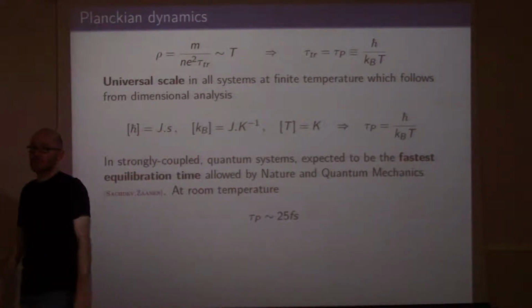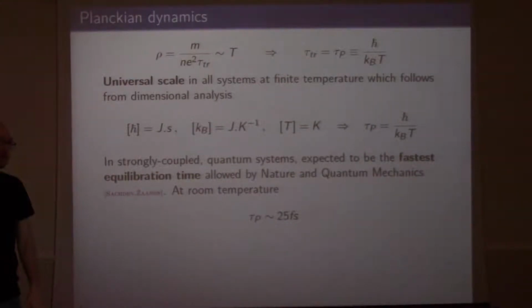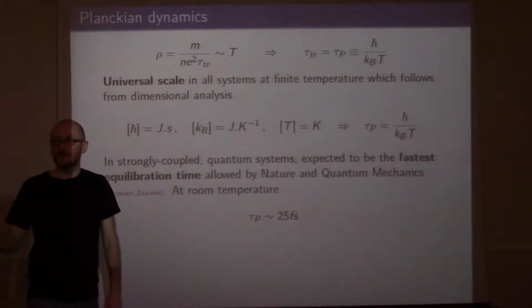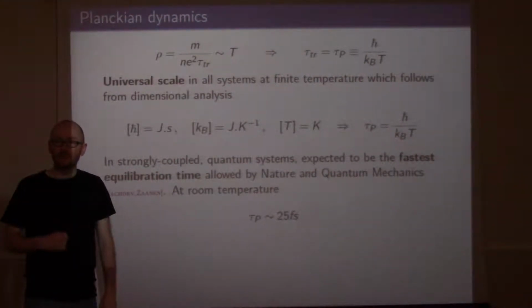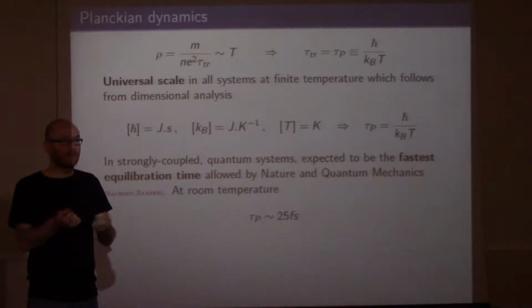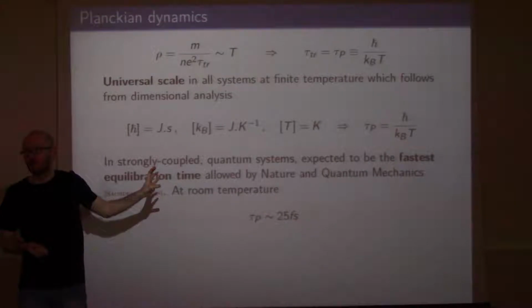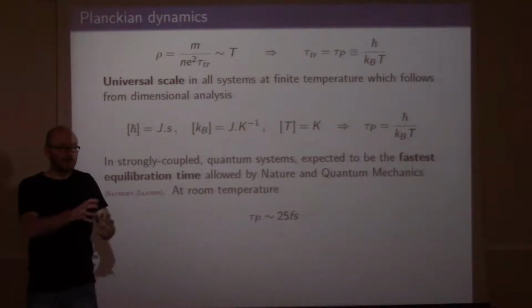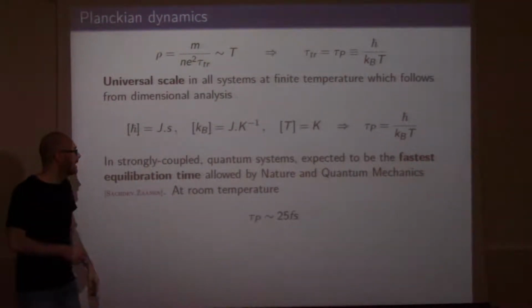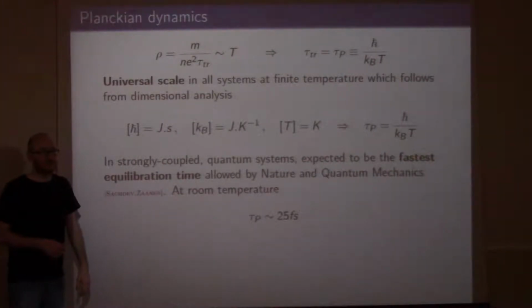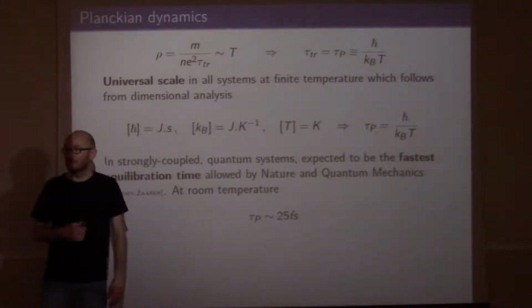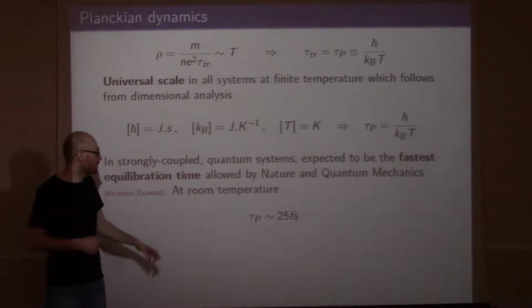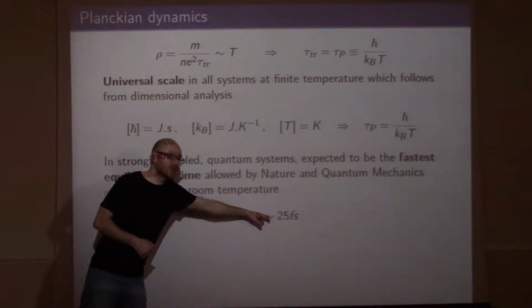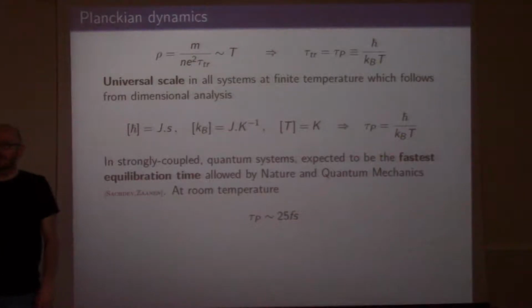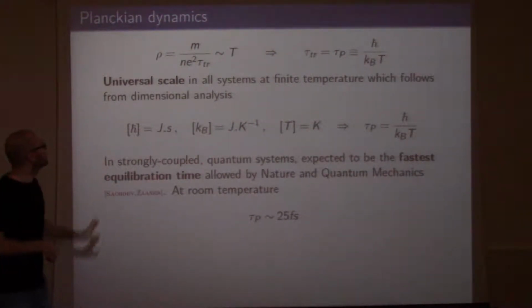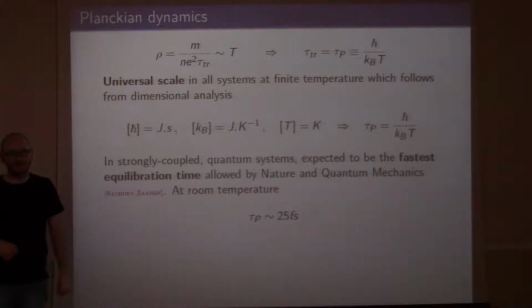Now this is a timescale that appears all over the place in, say, quantum criticality. At a quantum critical point, you essentially have a scale invariant description, you have a CFT, and then temperature is the only scale that you can use in order to make up for the scaling dimensions of any observables. So this would be the natural timescale in any quantum critical system. It turns out that in many of these bad metals, we believe that there are quantum critical points around, so it somehow connects to this picture. It's also expected to be the fastest equilibration time that nature and quantum mechanics allow, again by Heisenberg uncertainty principle arguments. And indeed, when you plug in numbers, at room temperature, this timescale would be 25 femtoseconds. That's an extremely short timescale in terms of experimental timescales. So somehow this linear resistivity is suggestive of this Planckian dynamics.